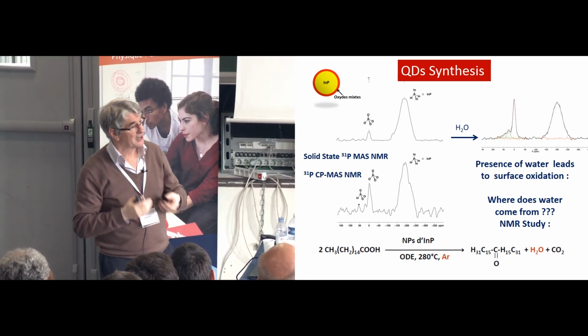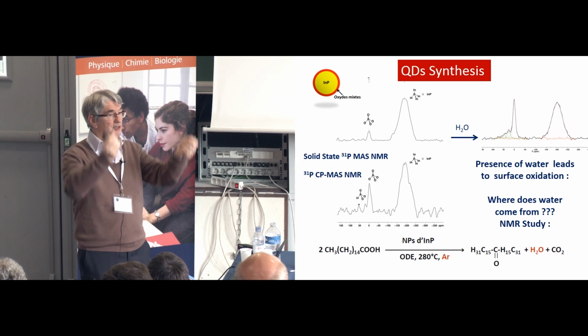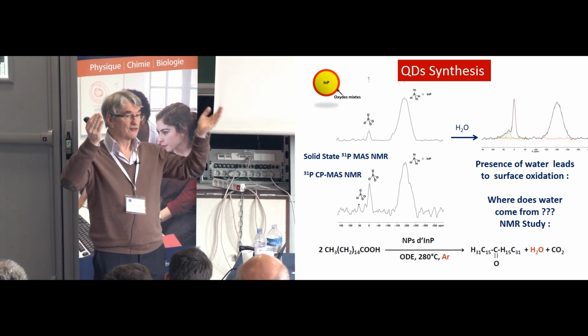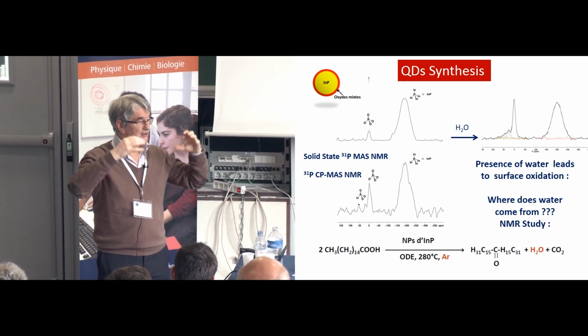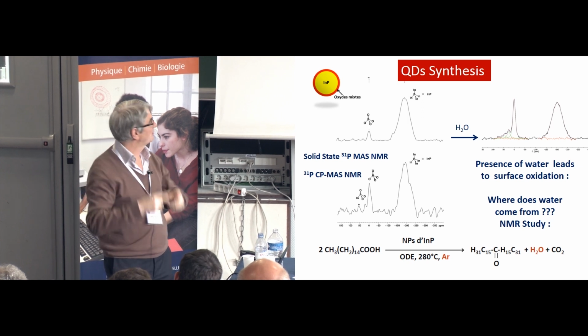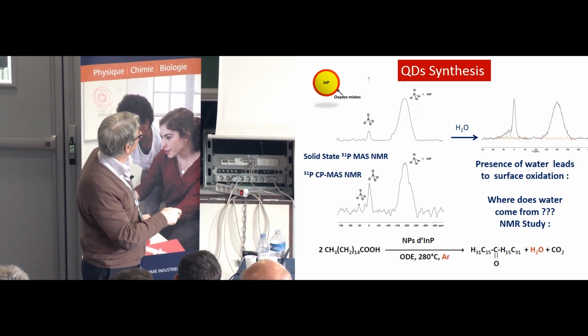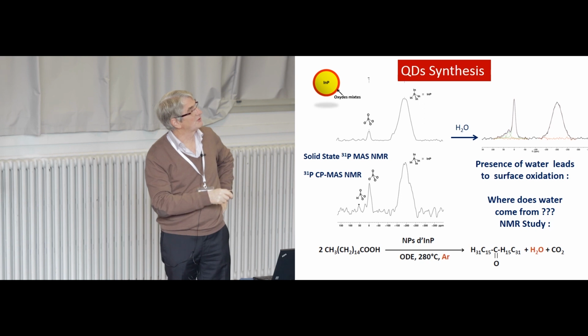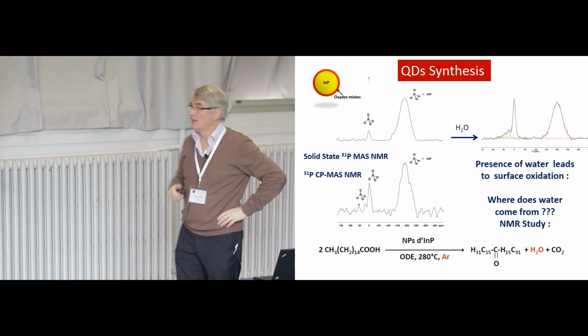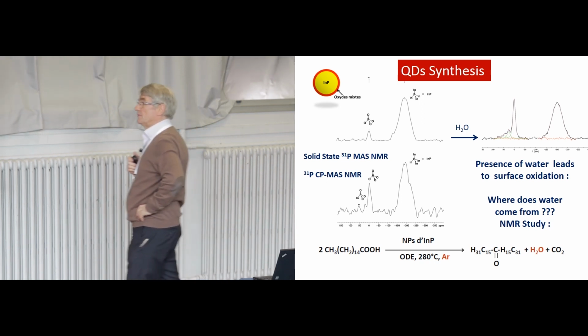So what you expect is that the outside peaks will increase their intensity, and the inner peak will decrease their intensity. And what we see is that the phosphate increases in intensity. So where do they come from?